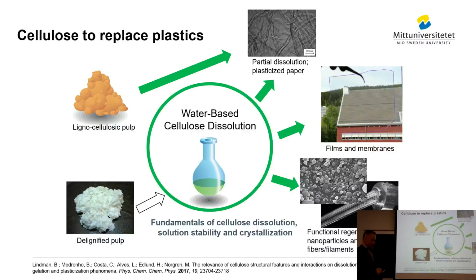We have been working with treating lignocellulosic pulps. They are not dissolving, but they are partially dissolving. So you can use that for plasticization and other things that make the material a bit different from, for instance, ordinary fibers. And of course, if you go to a much better pulp where you have high cellulose purity and not too high DP, you are able to completely dissolve this material, and that is what we are doing also.